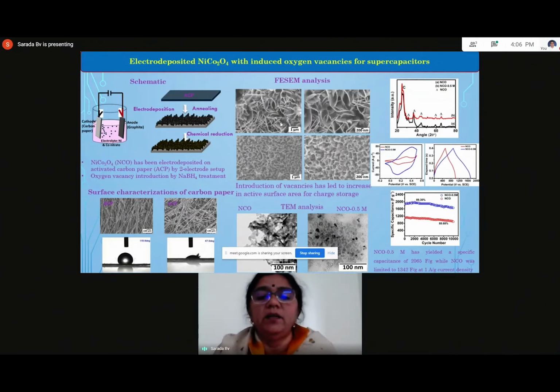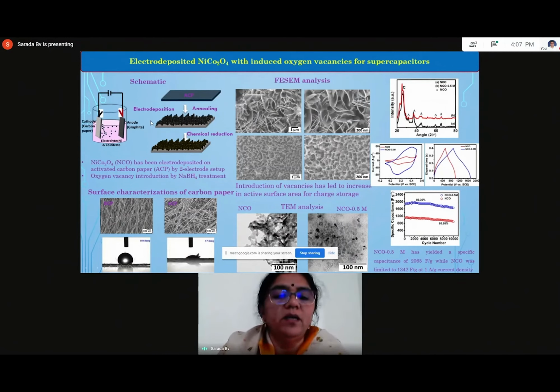In addition, this work is done by Ms. Samhita. Again, I'm proud to say that she is also an alumna of Anantapur campus, and she is doing her PhD with me. She is registered at IIT Hyderabad. Of course, she is a research scholar at ARCI, and she is working under me. And she has made these electrodes, and she has shown that by creating oxygen vacancies in the electrodeposited nanostructures of nickel cobalt oxide, which is a transition metal oxide that gives the highest energy density and specific capacity among the metal oxide pseudocapacitor materials.